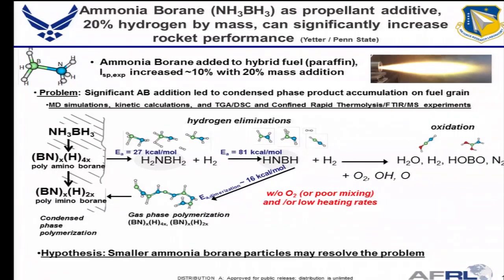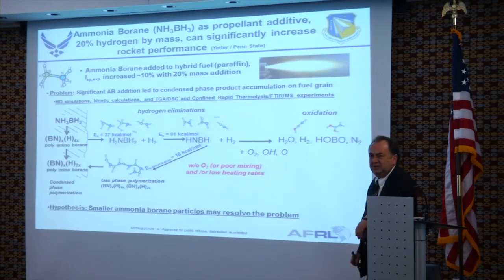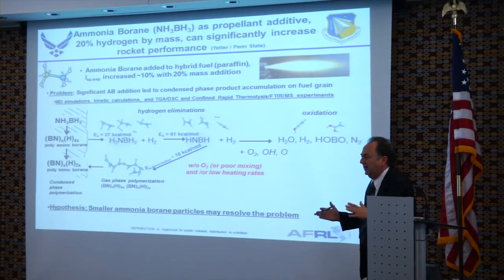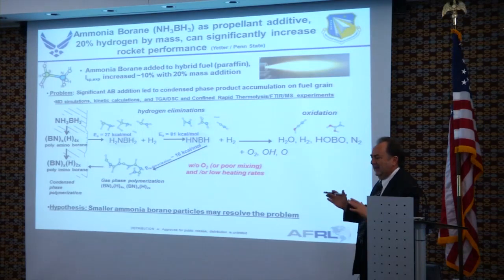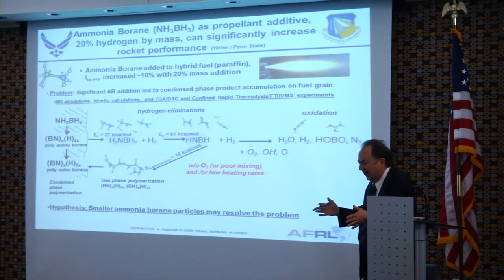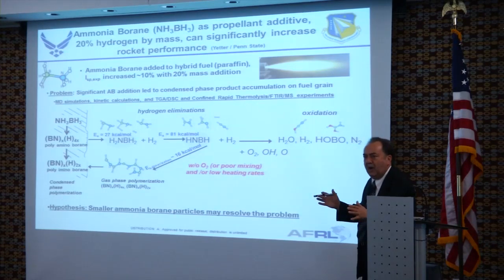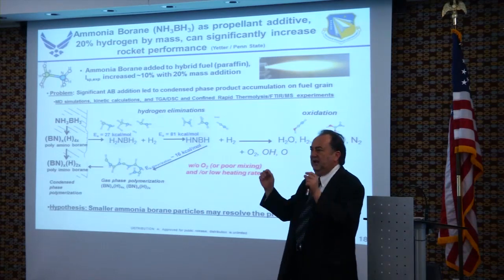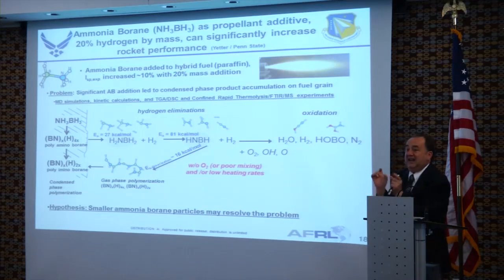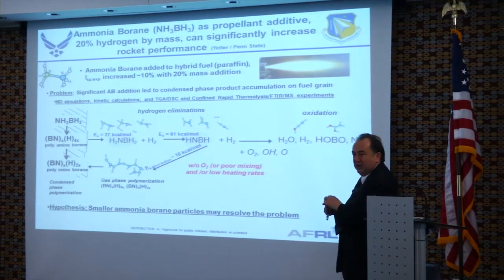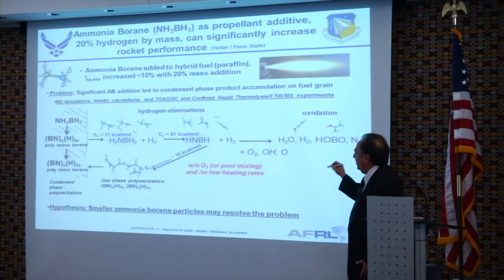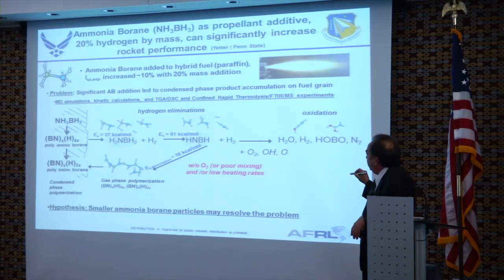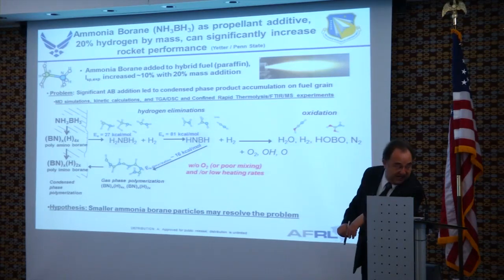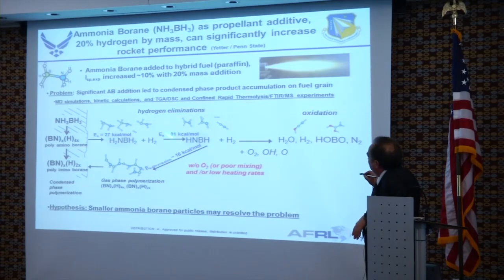This is one modeling technique called reactive force field. I think John talked about it a little bit. This is something for when it's too hard to do quantum mechanics; it sits between quantum mechanics and molecular dynamics. In that field, you just find bond forming and bond breaking energies as a function of the atomic distances. When the molecules get closer, then they form something. When they do that, it's much faster than quantum mechanics, and they did that at Penn State. Okay? In those calculations, in addition to density functional theory, and also finally the Arrhenius kinetics, which we can, okay, I'm getting there, which we can get.